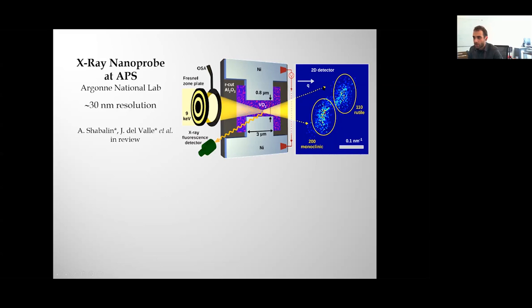And then you can take the 2D diffraction map coming from that spot. And this is what you see here. So here you can clearly see the two peaks corresponding to the two phases, one corresponding to the low temperature monoclinic insulator and one corresponding to the high temperature rutile metal. So this allows you, with 30 nanometer resolution, to determine what is the phase fraction, how much metal and how much insulating you have at that point.